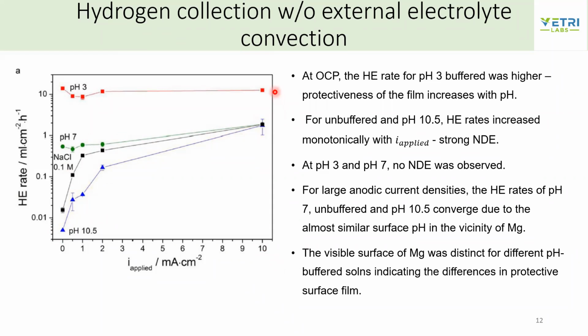After all these experiments, they were also able to visibly see that the magnesium surface was distinct, meaning the oxide or passive film that formed had differences in color—some were black and some were lustrous. So they were able to clearly attribute the differences to the differences in the passive film.